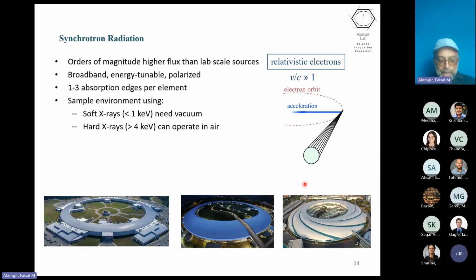So now I'm going to get to the question of what is the locality part of this. So why is it that there's a challenge to doing these kind of measurements locally? And the reason is, as I suggested for X-ray absorption, you need an energy range over which you're going to scan. For X-ray emissions, this is not a necessary condition. However, for X-ray emission, if you want to be close to the energy that triggers the core hole process to begin with, that gives you a much higher cross section.